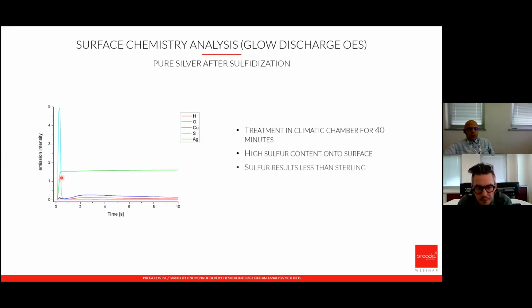The direct sulfidization test on pure silver showed a high presence of surface sulfur, higher than its corresponding xenotest, but lower than sterling silver, probably because of the absence of copper in the metal, which has a crazy strong affinity for sulfur.